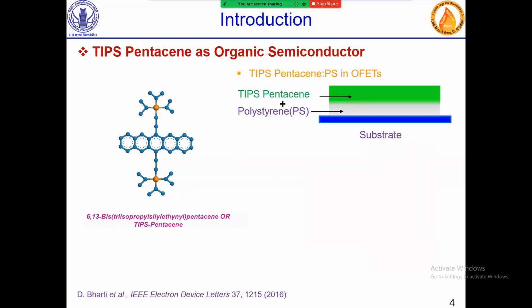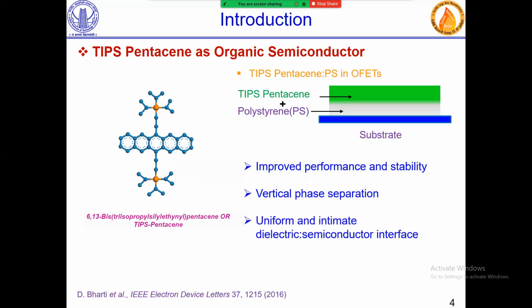This is the basic structure of TIPS-Pentacene. The reasons behind using this are solution process, high air stability, and low cost. In this study, we are using TIPS-Pentacene blended with polystyrene. We blend polystyrene because it provides a smoother surface with drastically reduced charge trapping, and also improved performance and stability. There is a vertical phase separation between TIPS-Pentacene and polystyrene. We get a uniform and intimate dielectric semiconductor interface from this.